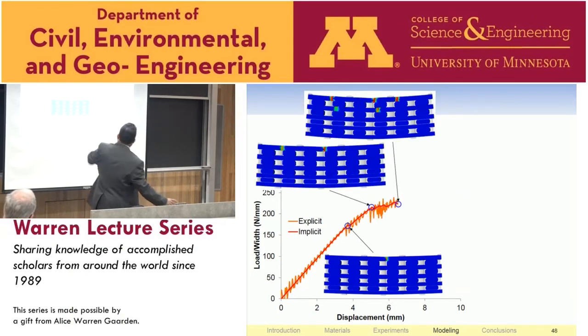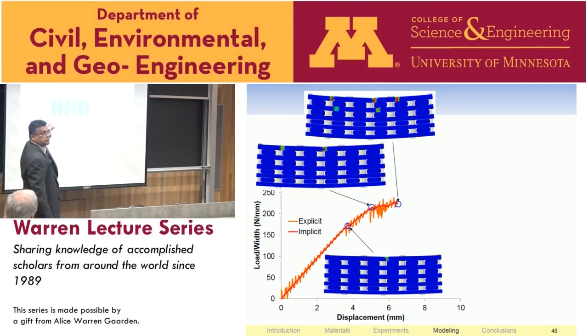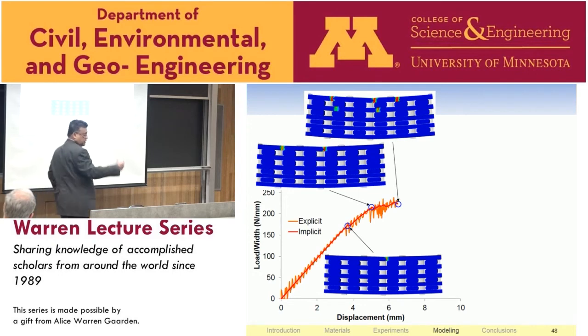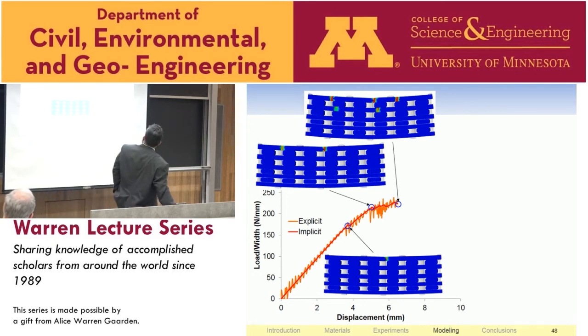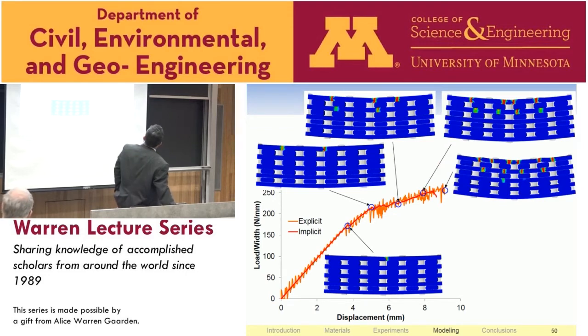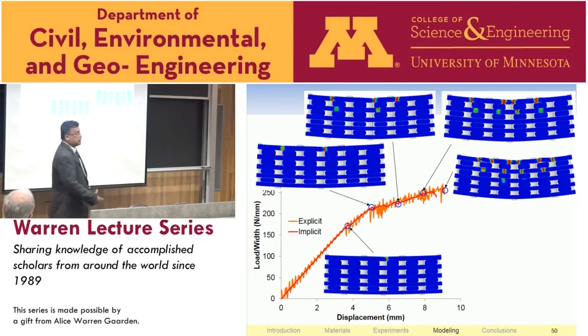You can see a first kink band forms just like in the experiment on the compression side first, and then you see the kinks multiplying, right? More and more kinking occurs as load increases. There's no abrupt failure. The load keeps increasing still, right? Until there is sufficient kinking and the bottom side starts to fail in tension, where the tows rupture on the tension side. These are the tows only.